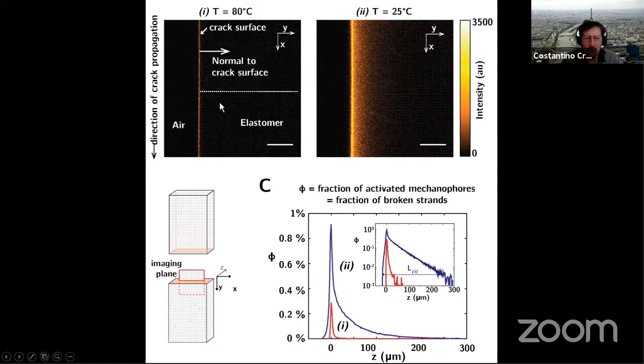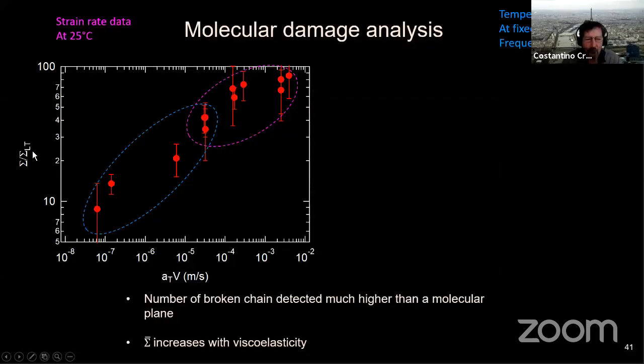If you plot now the data in a quantitative way, you can plot this relative to the Lake Thomas prediction. And you can see that we get between 8 and 80 times the Lake Thomas prediction. Even at 80 degrees, we still break significantly more than a monolayer in terms of bond breakage. So we're not yet at a threshold condition at that temperature. But if you remember the data on the fracture energy, it doesn't look very different. And I'm going to give you more comparisons later.